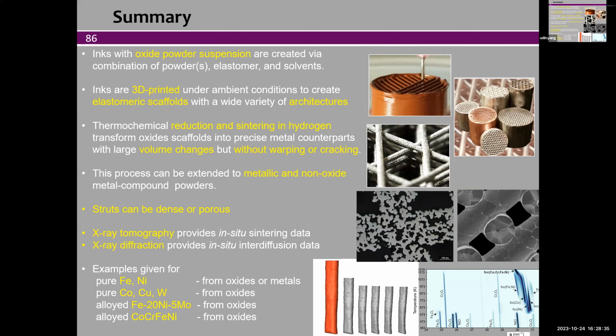One more question. Okay. So I'm wondering what limits the resolution of the printing, for maybe the thickness of the struts? Is it the rheology of the polymer or the strength? It's very practical. It's really the clogging of your extrusion syringe. So we can get them all the way down to 50 micron, right? Especially for polymers or for liquids, it's relatively easy to extrude 50 micron.